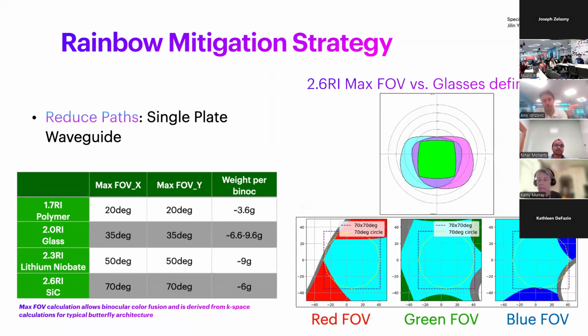Now, when you plot the max field of view allowed by the silicon carbide overlaid with the limits of the display field of view as defined by typical prescription glass frames, you can see that it is almost approaching the max limits. It is important to note that the actual white field of view is smaller at the corners due to the dispersive nature of the SRG gratings, which is determined by the intersection of the red, green, and blue field of views. However, if you allow some perceptually acceptable amount of binocular fusion, we can get pretty close to the max extents with silicon carbide.